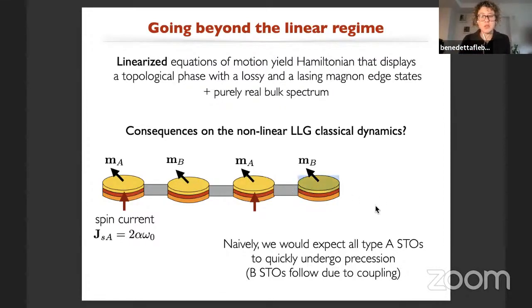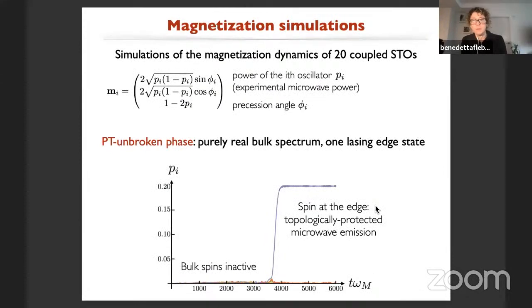Let me show you what we actually observed. We simulated the nonlinear LLG equation. I'm parameterizing the magnetization by some precession angle and by the microwave power that the magnetization precession can emit. So here we are running the simulation for the PT unbroken phase. Let me just remind you, we have a purely real bulk spectrum and one lasing magnon edge state. So this was in the linearized picture.